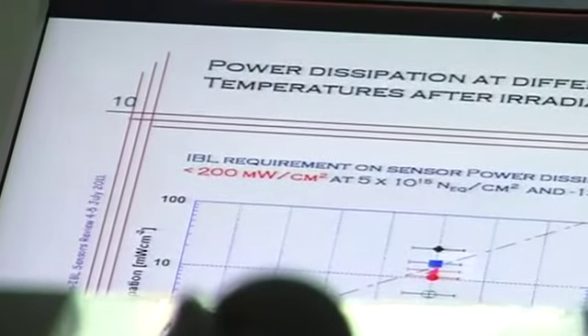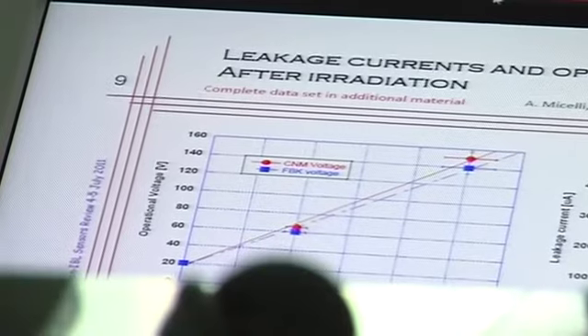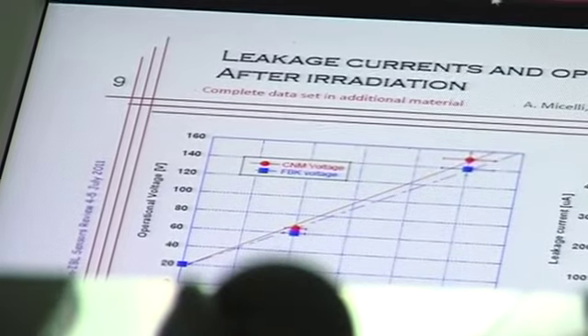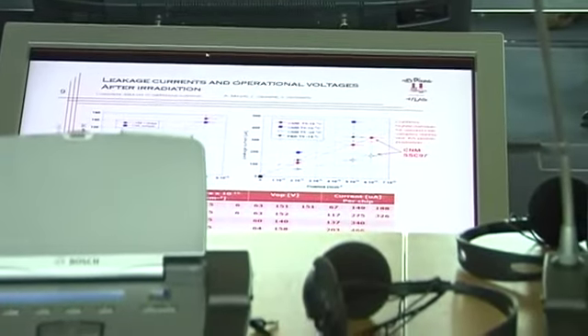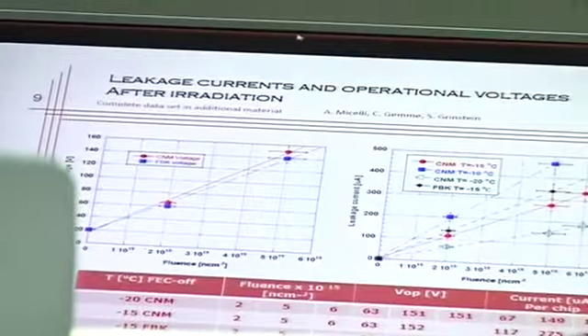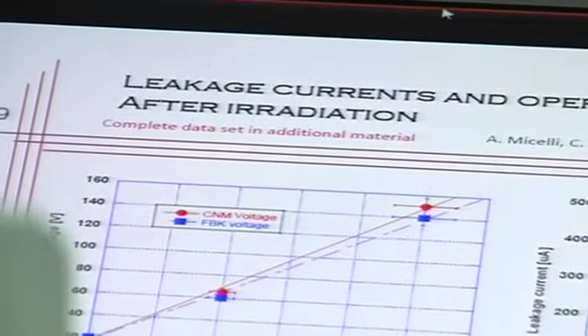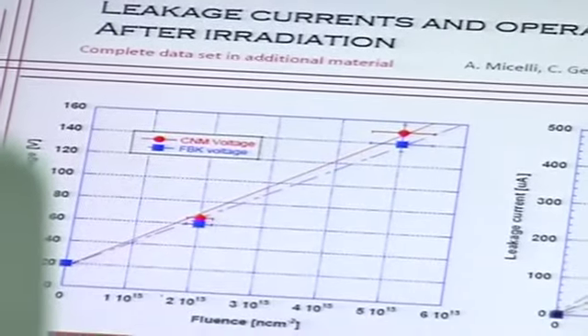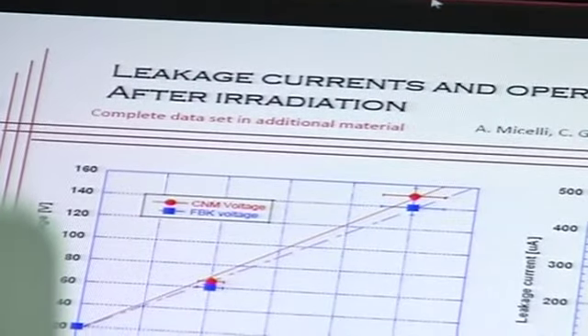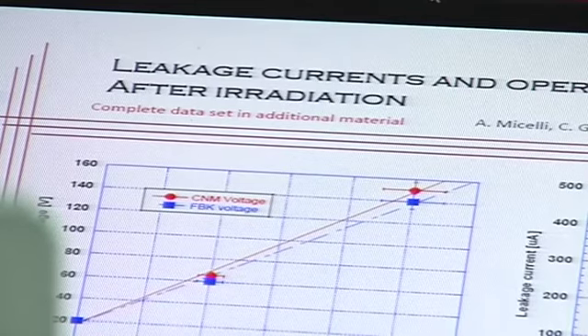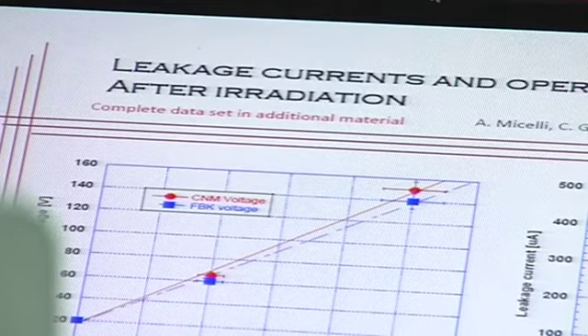How do you define the operational voltage after irradiation? So we first of all estimate that with simulations, and also we are trying to place ourselves in a region where we can operate stably and getting out the maximum amount of charge that we aspire. Stably in which sense? I mean, what is a stability parameter? I show you in a moment. Stability is, for example, a long time in this condition at fixed temperature where you're not really seeing a variation of the leakage currents. But I show you in a moment what this means.